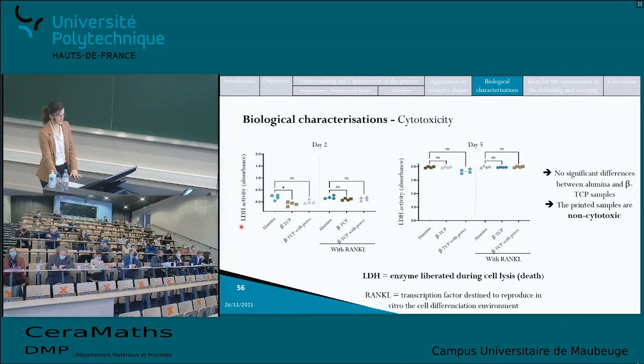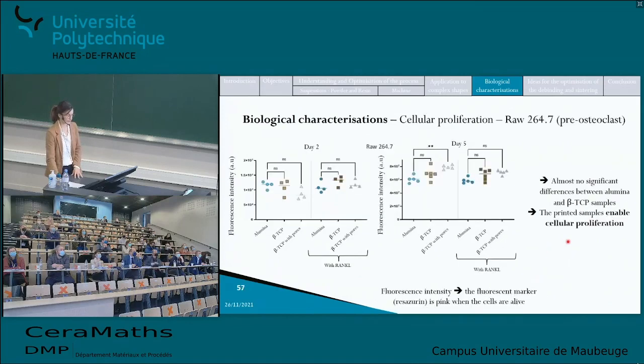And it appears that there is no significant difference after 2 days and after 5 days between the alumina samples and the β-TCP samples. So the printed samples appear to be non-cytotoxic, because the alumina samples are known to be non-cytotoxic. The second step was to evaluate the cellular proliferation on the samples. So here again, there appear to be no differences between the cellular proliferation after 2 days and after 5 days between the alumina samples and the β-TCP samples, except here where the cell proliferation is even higher on the samples produced with β-TCP, on the sample printed with pores. So there is almost no significant difference. So the printed samples seem to enable the cellular proliferation at least as well as the samples produced with alumina powder.